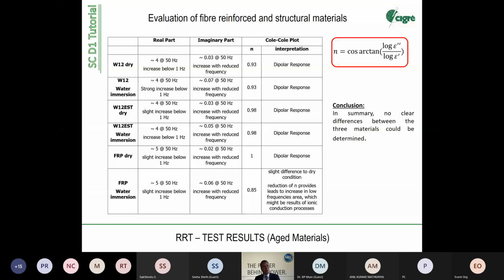because when we talk about thermally initiated breakdown, which is one of the long-term breakdowns, it's driven by a self-accelerating loop: the temperature increases because the losses are increasing during stress, losses are increasing with temperature, and so on. Temperature is increasing, so we have materials running into thermal-electrical breakdown, and this could be a warning sign. Lowering N increases the risk of entering a thermal breakdown.